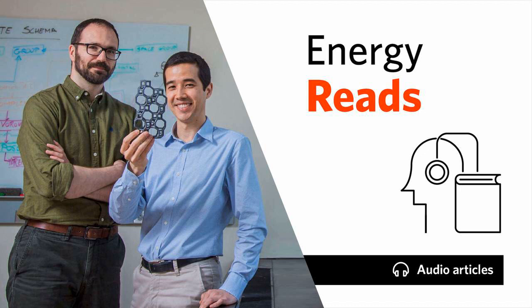One set of experiments focused on a zeolite called chabazite, which is used in catalytic converters for vehicles. Using their techniques, the researchers designed a new templating molecule for synthesizing chabazite, and the experimental results confirmed their approach. Their analyses had shown that the new templating molecule would be good for forming chabazite and not for forming anything else. Its binding strength isn't as high as other molecules for chabazite, so people hadn't used it, says Gomez-Bombarelli.